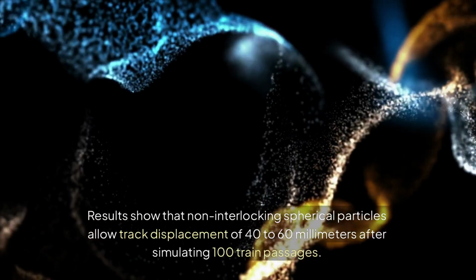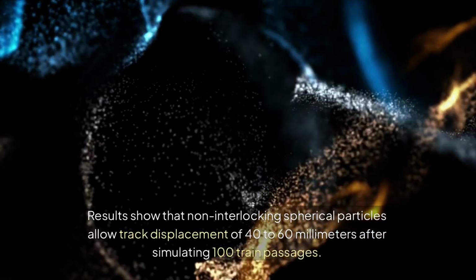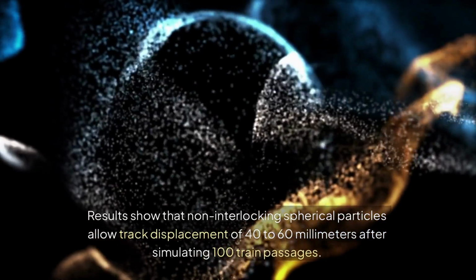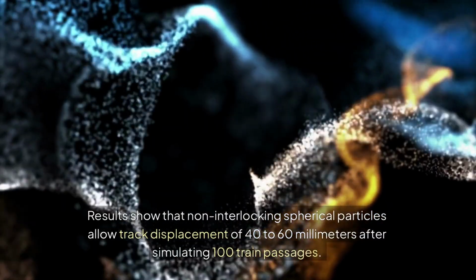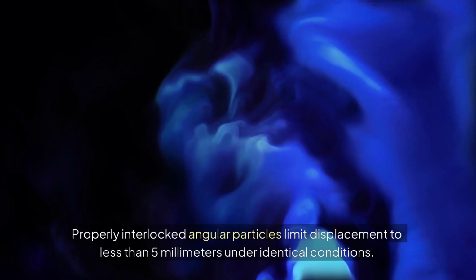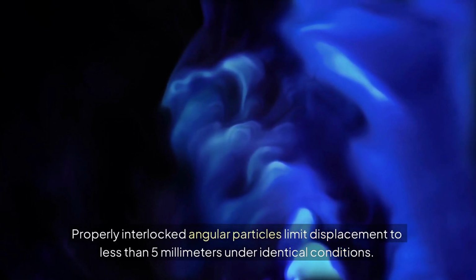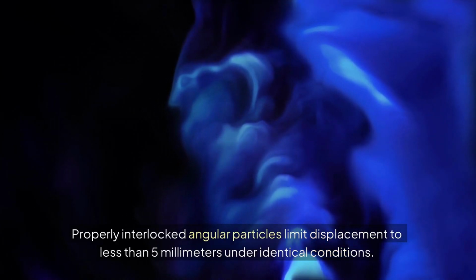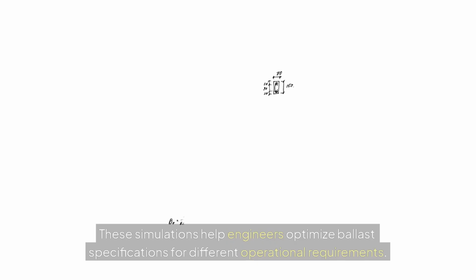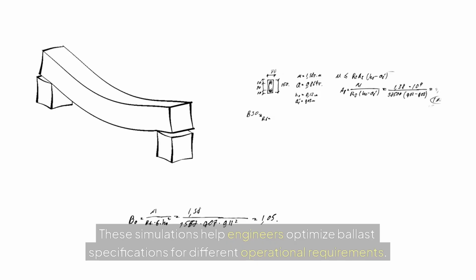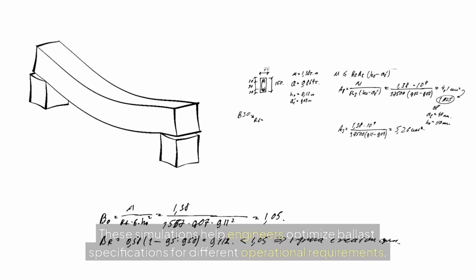Results show that non-interlocking spherical particles allow track displacement of 40 to 60 millimeters after simulating 100 train passages. Properly interlocked angular particles limit displacement to less than 5 millimeters under identical conditions. These simulations help engineers optimize ballast specifications for different operational requirements.